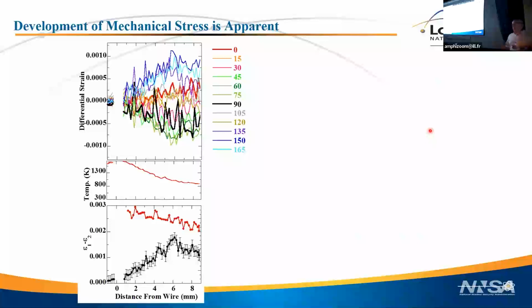We can watch the stress develop now. So this is again looking at the lattice parameter as a function of angle. Now I've subtracted off the average lattice parameter so it shows up more, but you see how the strain, if you will, is angle dependent. That's the mechanical stress evolving. What you can really get, because I don't have any reference lattice parameter as a function of temperature, so I can't get an absolute strain. What I can do, though, is subtract the two strains in the opposite direction, because if you subtract, then the reference subtracts out. And that's that difference here.